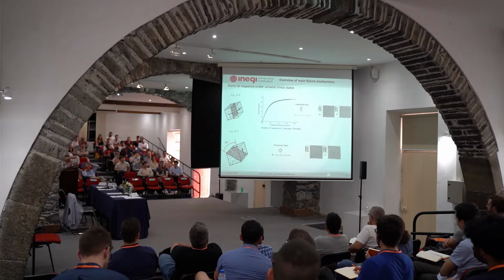Okay, and then we can get all these cracks and then unstable crack propagation. Okay, very quickly, shear. We've seen this, we've seen also from the tests. You get in-plane shear. You get this crack which is perpendicular. You get all this nonlinear response before failure, and transverse shear.